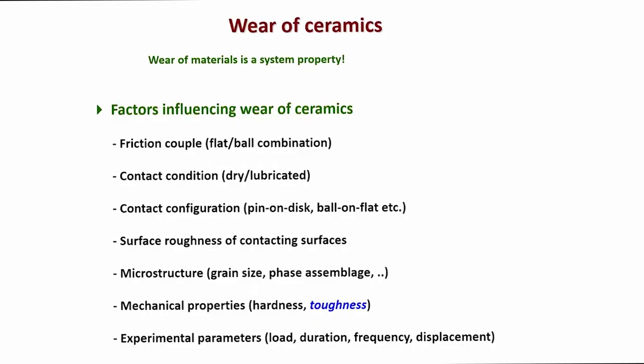Or in other words, is the toughness for transformation toughened ceramics important, and therefore, should the toughness of the transformation toughened ceramics be carefully tailored in order to develop materials with tailored wear resistance property? This may not be the case for non-transformation toughened ceramics like alumina or silicon carbide, but for zirconia it is fairly important, as you will see in the next 15 minutes or so, that our results have shown a few years back that it is indeed important to tailor the fracture toughness in order to optimize the wear resistance property. Now, let us go back to the slides again.